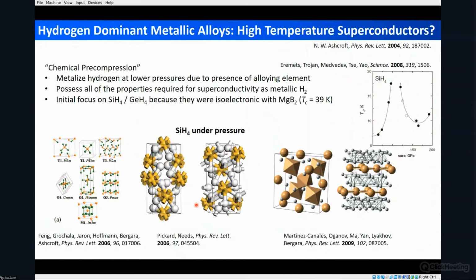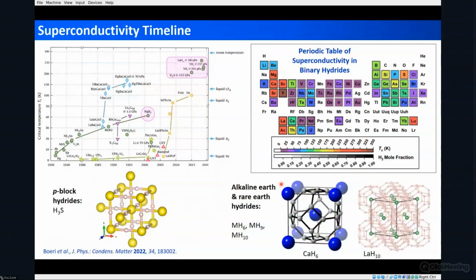Nonetheless, this really brought about a large number of people doing computations trying to predict the crystal structures of high pressure hydrides mixed with some other element, and then also followed by other experiments. And so here I show that, about a decade later, pretty much all of the binary hydrides have been studied computationally. And this is the periodic table of superconductivity in binary hydrides that shows a number of the trends that Julia already emphasized. And if you have the addition of an electropositive element, such as an alkaline earth or a rare earth metal with hydrogen, you get the highest predicted TCs, of course, under pressure only.